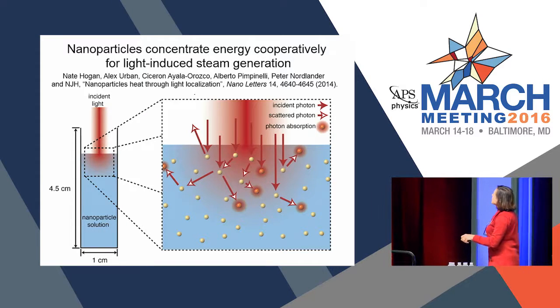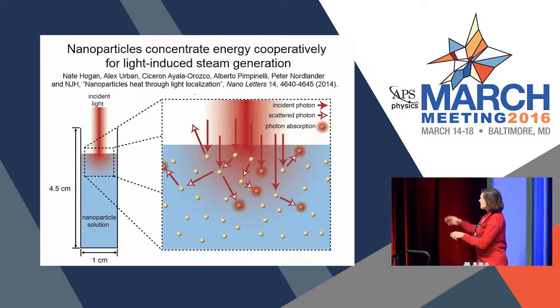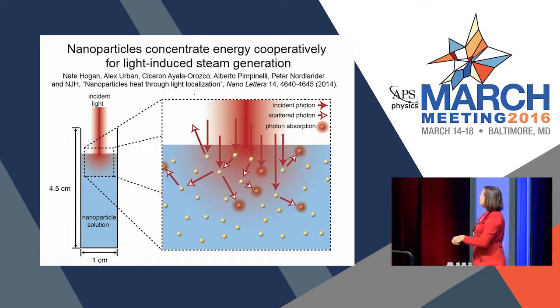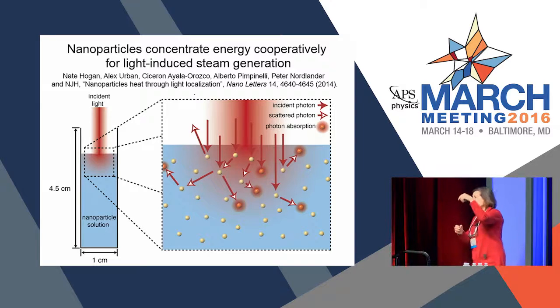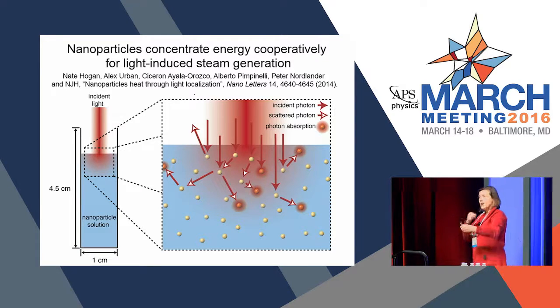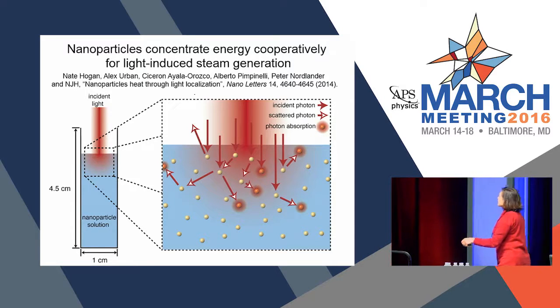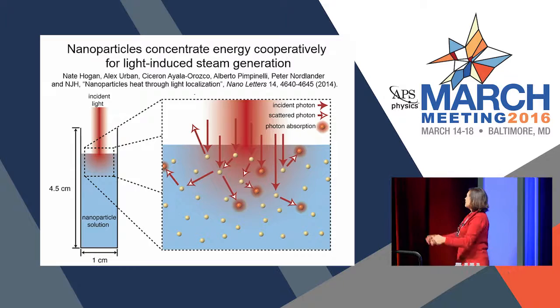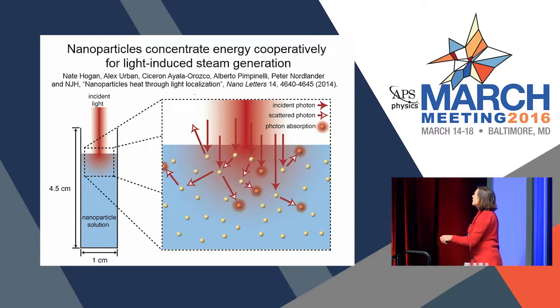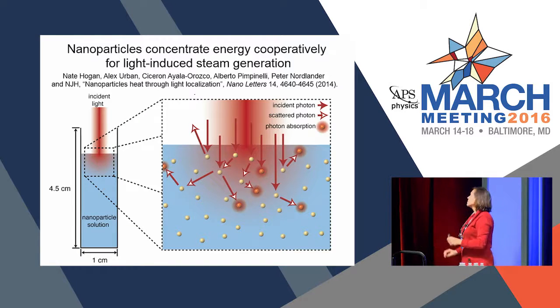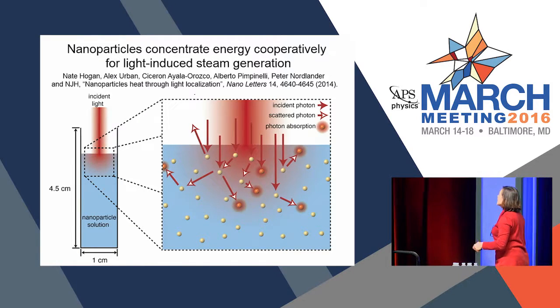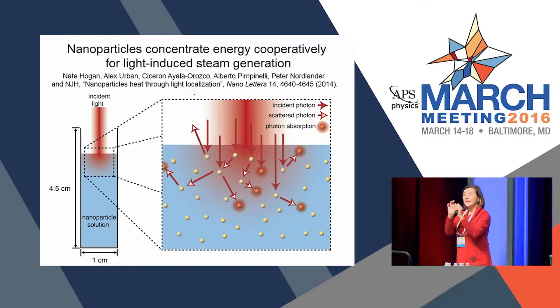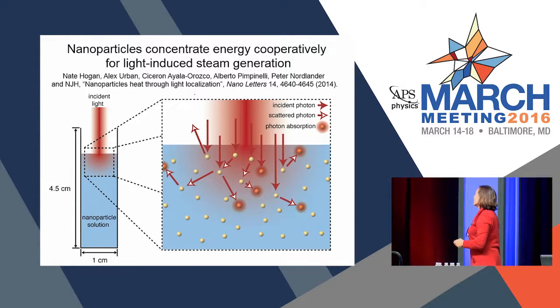But if we think about each individual photon entering the flask, so this is just a cuvette irradiated from above, and we have nanoparticles that both absorb and scatter light. Each incident photon will scatter once or twice or some multiple times until it gets absorbed. This multiple scattering, which is a function of the concentration, will confine the light energy into the thin region near the water-air interface, where the absorption then occurs as well. So the light energy gets absorbed in this very thin layer near the surface.